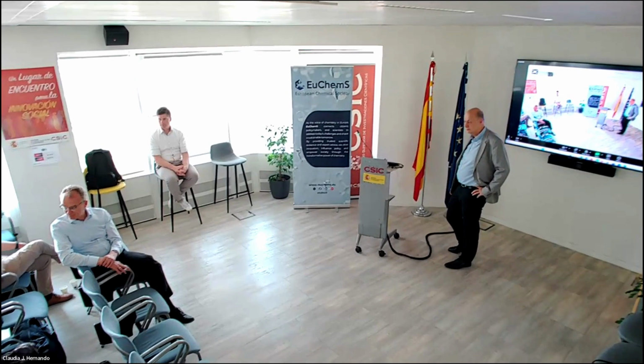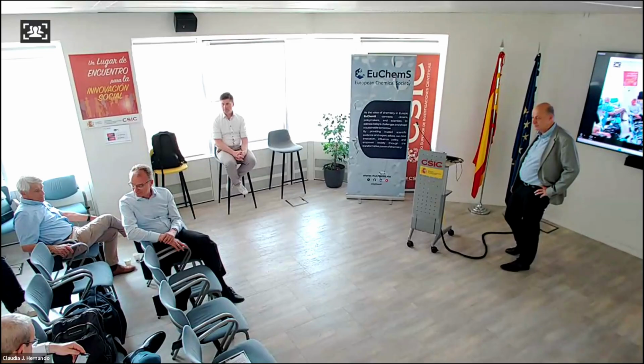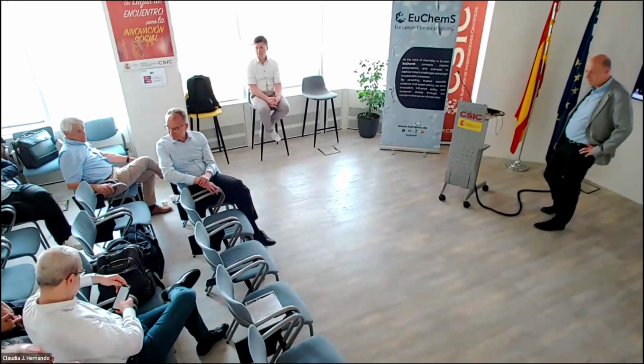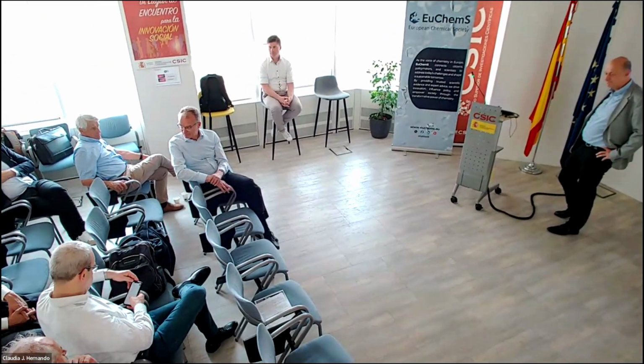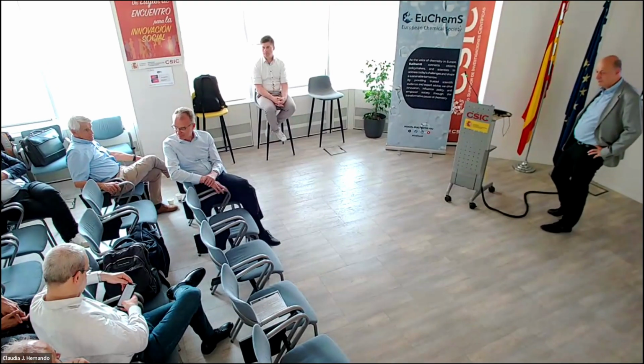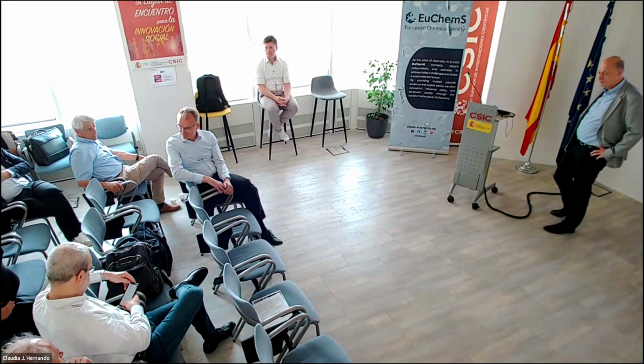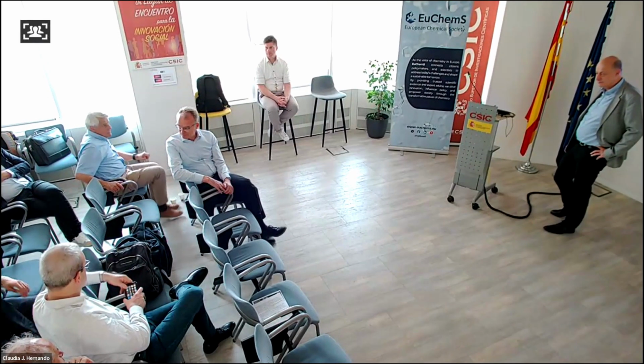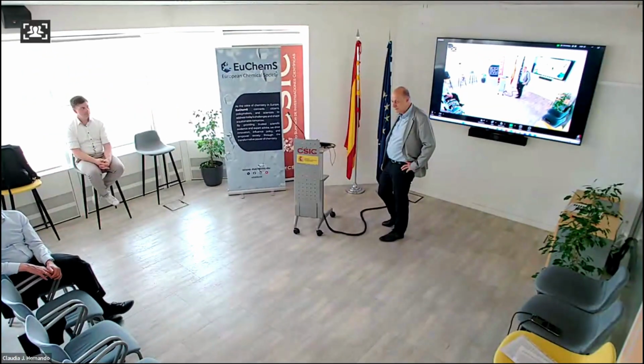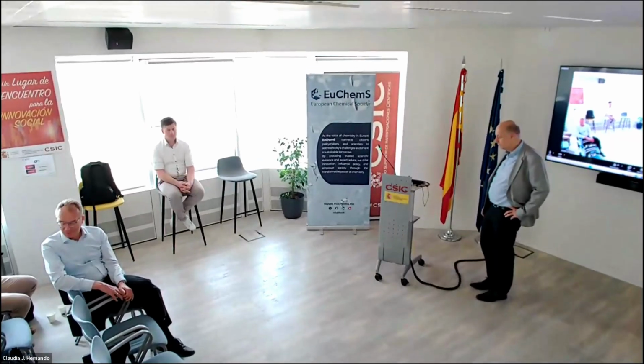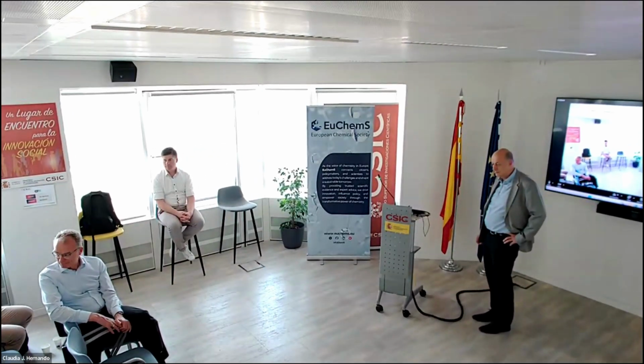Yeah, so you have a reaction. You obtain a product. But because of the absence of the stabilizing ligand, palladium or platinum is reduced to the metallic state. But they have the technology to recover it, to reconvert it to palladium acetate. Unfortunately, no similar technologies exist for the rare earth elements for the moment.